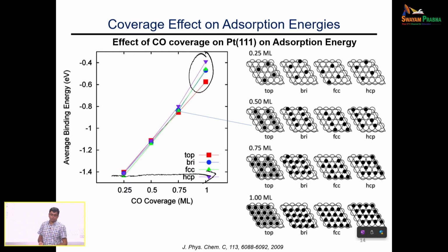So if I say adsorption energy of CO on platinum, for example, is 140, this 140 is valid only at a coverage of 0.25. So when you have adsorption in practical scenarios, that is something you need to think about, and that's where the isosteric heat of adsorption becomes useful, because it tells you what the heat of adsorption is at specific coverages that you have, okay? And that's precisely something that we can estimate this way as well.